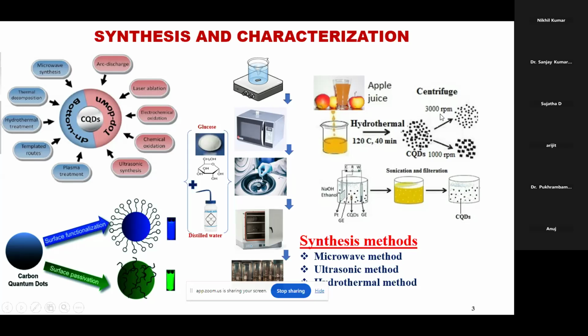After that, centrifuging also plays a role, because besides cleaning, it also breaks up the particles. So 3000 rpm gives one emission wavelength, and 1000 rpm gives the red emission. Maybe when the size increases, the emission also differs. Then sonication is another method.